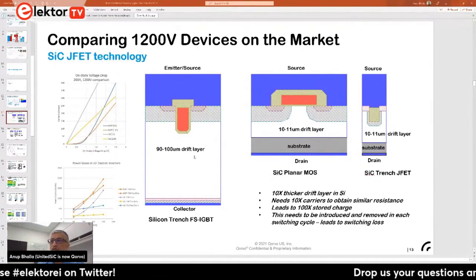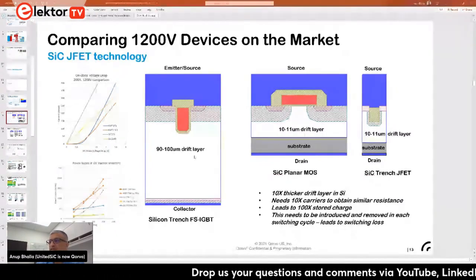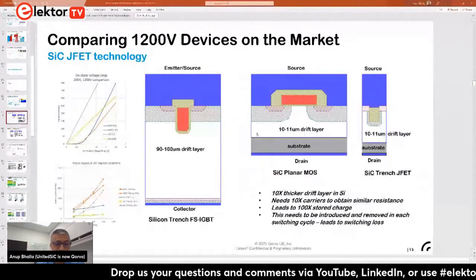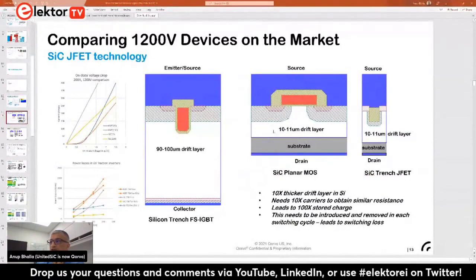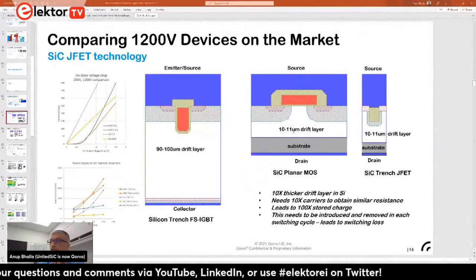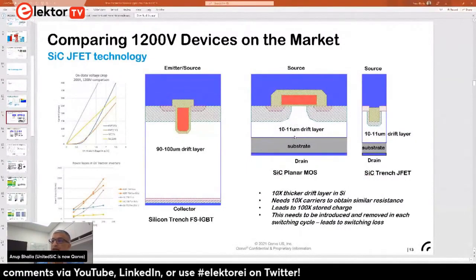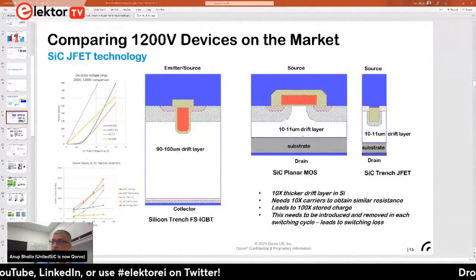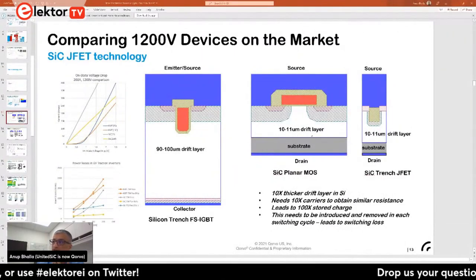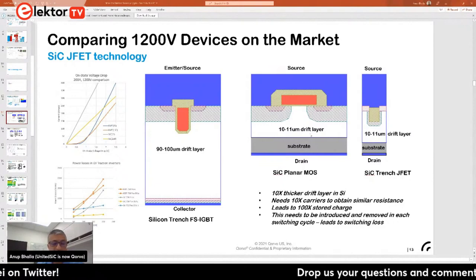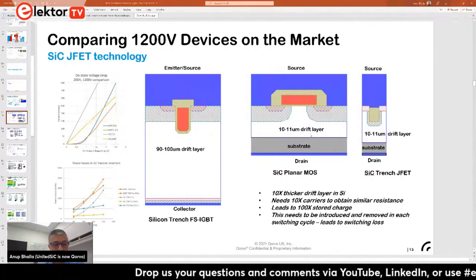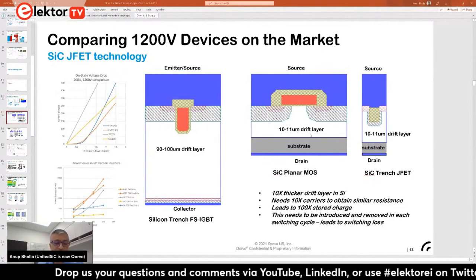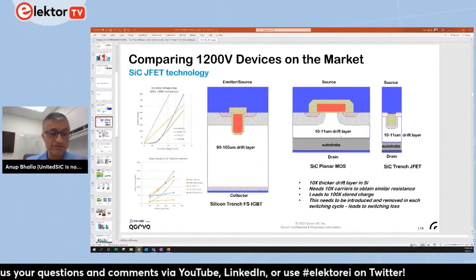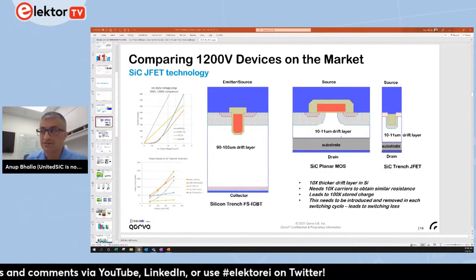So if you wanted to switch high voltage devices very quickly or losslessly, this is where wide bandgap devices come in, because with their high critical field, like 10 times higher critical field, you can theoretically have a 10 times thinner region to support the voltage like I'm showing here. It's called the drift layer. And then there's no need to inject carriers anymore. So you're just charging and discharging capacitances. And this allows these devices to switch much faster. So that's the whole value proposition for wide bandgap devices.